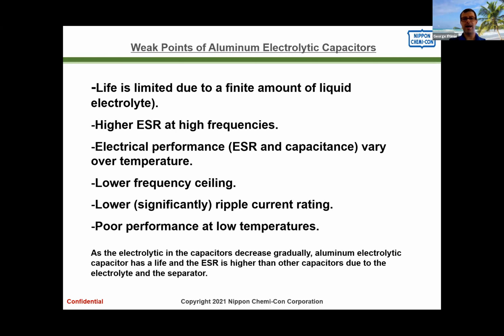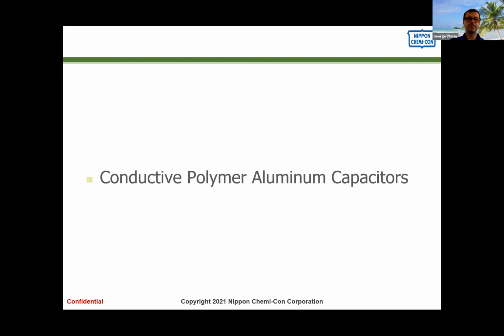I've seen a lot of design issues with customers where they didn't take the low temperature performance into account. They assume that whatever happens on a bench will continue. And of course, it doesn't, especially at very low temperature, below -40 degrees C. On some capacitors, especially high voltage, you can lose over half of your capacitance, and your ESR could be 4 or 5 times higher at those temperatures. It is transient. It will not damage the capacitor. But essentially, at low enough temperature, you're going to have a block of ice. You're really not going to have a capacitor there anymore.